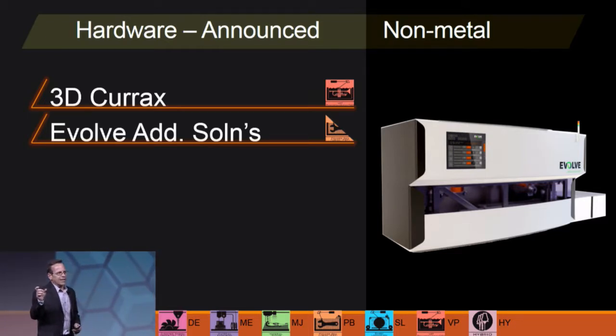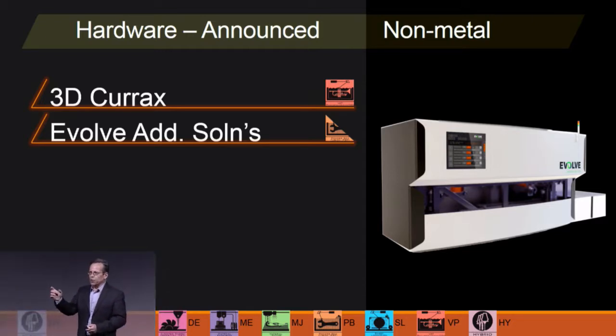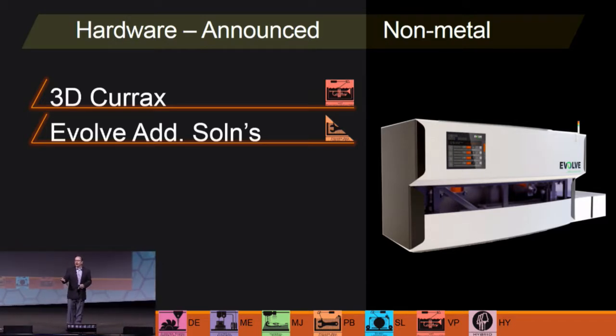The next word is electrophotographic. And if you're from the 2D printing world, you'll know what that term means. It's used in high-speed, high-volume, multicolor printing. And Evolve has actually partnered with a company that has been putting those units in place for a number of years. Electrophotographic, to boil it all down to the simplest terms: a drum spinning that's electrically charged, powder that's also electrically charged, the opposite charge, which is attracted to the drum one layer profile at a time, transferred, a little bit of heat, a little bit of pressure, and you have your 3D printed parts.